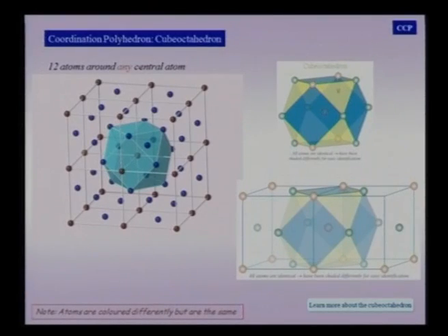Now if I cut deep enough, then I will be cutting into these edges which were originally the vertices of the cube. Now if I cut deep enough, then you will see that these faces which are cut faces become triangular, and the remaining faces, which if I cut a little bit, these blue faces, will be hexagonal, but if I cut deep enough, they will become squares, and therefore I get a cube-octahedron. Now in terms of the simple rotational symmetries, the cube-octahedron is exactly identical to that of a cube and is the coordination polyhedron in the cubic close-packed structure.